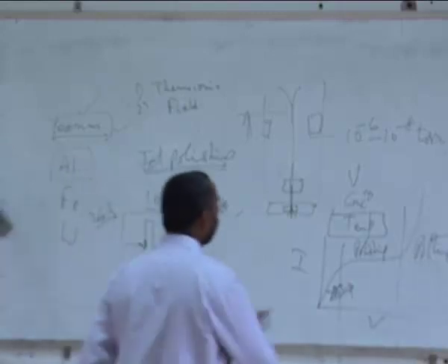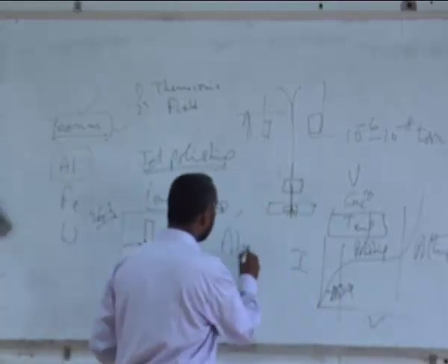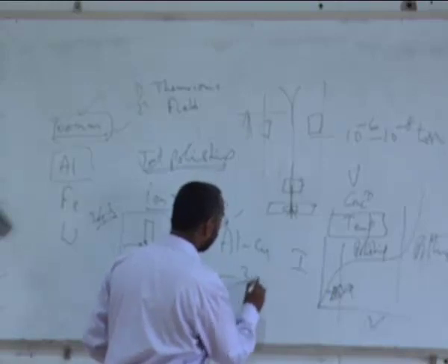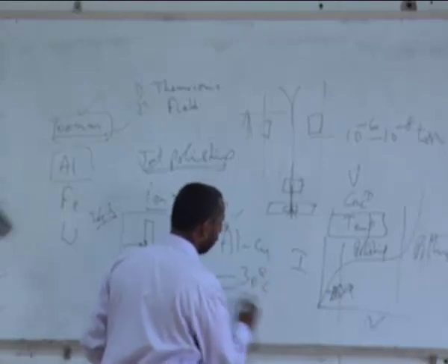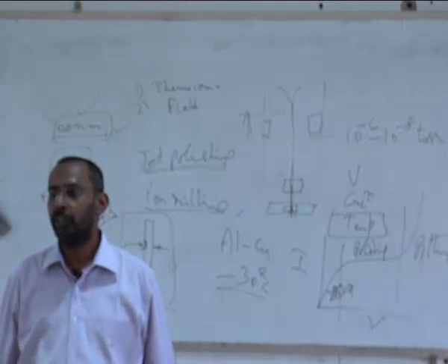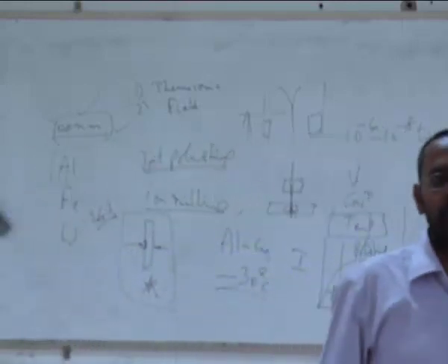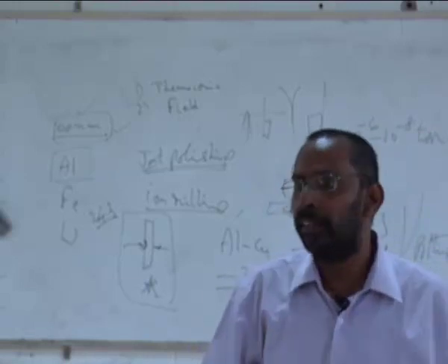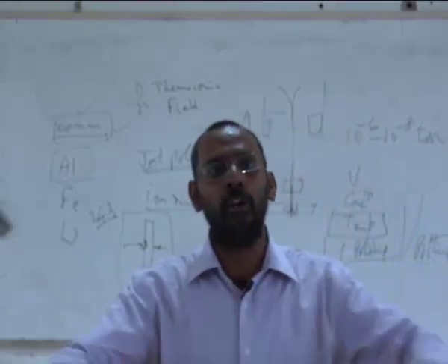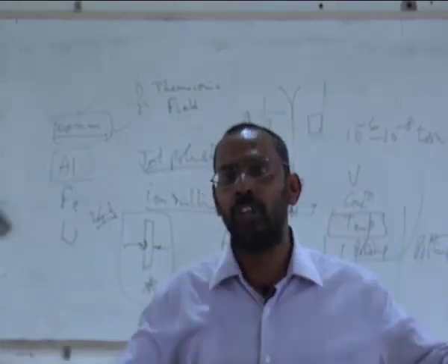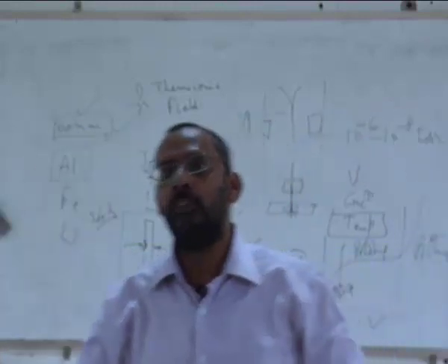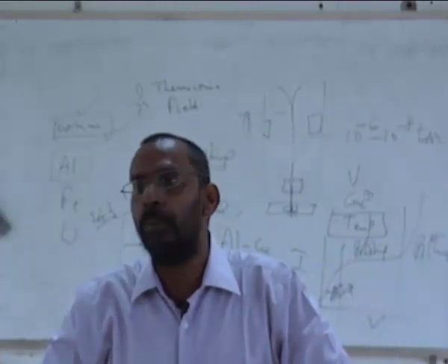So in most cases, for example, if I am making an aluminum copper alloy, generally we use about minus 30 degrees centigrade. So you cool the whole electrolyte to very low temperatures using liquid nitrogen or something, and then keep the electrolyte at low temperature and allow it to circulate and then fall as a twin jet onto the sample and do the whole thing.